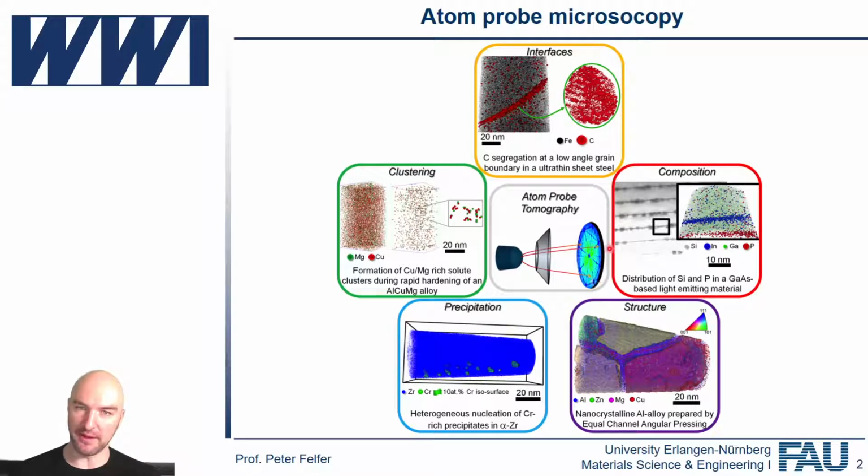So we have something macroscopic. We've got an image of the atoms of the sample in direct connection with something on the nanoscale. And this is where the magnification comes from. If you look at the tip radii, they're 50 to 100 nanometers. Again, it's something for later. Our screens are a couple of millimeters, a couple of tens of millimeters. So you can see we're at an order of magnitude of 10 to the 6 in terms of magnification.